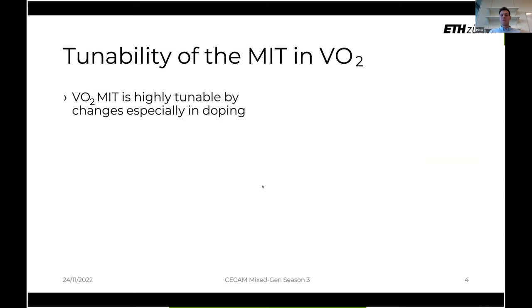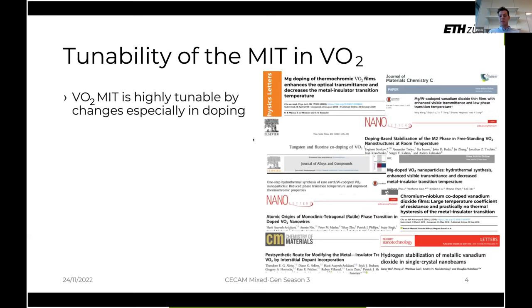affecting the metal insulator transition, and it is the point of tunability of the metal insulator transition in VO2. VO2 is interesting both because of its simplicity, but also because its metal insulator transition can be tuned very easily. There is a wide range of experimental papers here. I just selected a few, which look at various conditions. Very often, these are various dopants that are added into VO2 in order to change the hysteresis loop of the MIT that I talked about before. These try to either change the transition temperature, widen or narrow down the hysteresis loop, change the different heights of the resistivities, et cetera.